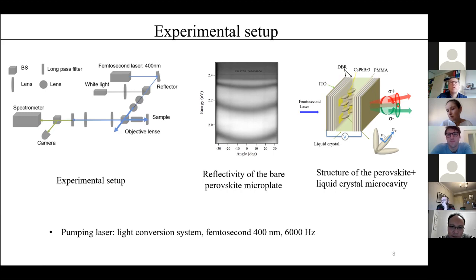Okay, so the liquid crystals on the surface of the perovskites are just oriented by the... No, sorry. I mean, we transfer the perovskite onto the surface of the DBR, and then we put the PMMA layer. So the liquid crystal does not touch the perovskite. Okay, so there is another PMMA layer at the top.